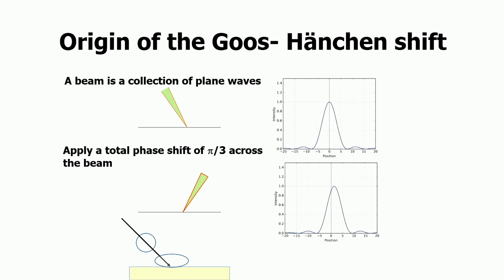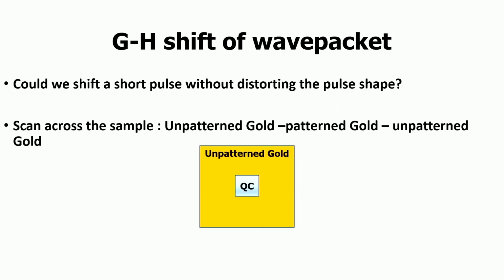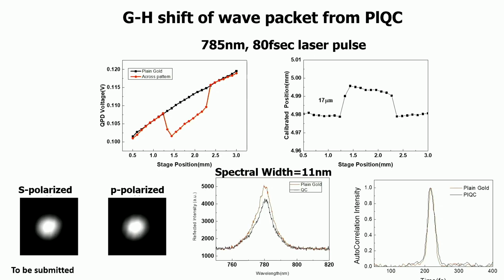So we showed that if you take a structure like this, this is the unpatterned gold region in which the central part is a quasi-periodic distribution of air holes. We measured the beam shift from each of these locations across the quasi-periodic structure and plotted it here. There is some slope here, which we correct for. So you get a 17 micrometer shift in the beam position when we go from unpatterned metal to the patterned metal region.